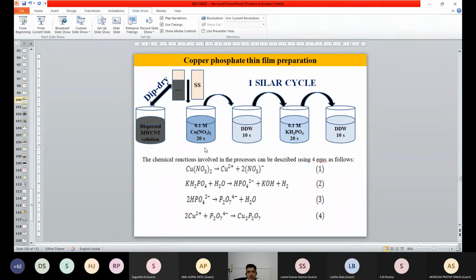So we have taken the copper nitrate, we have taken the source for the P, right? And we have used double distilled water as the ion exchange water. So we have used the carbon nanotube, which is coated on the stainless steel substrate, right? And we have dipped it inside the copper, then we have dipped it inside the P solution, that is KH2PO4 solution, so that you can get Cu2P2O7 on the carbon nanotube. And this is the reaction kinetics. So how we have proceeded with this reaction kinetics, chemistry people can understand in a better way.